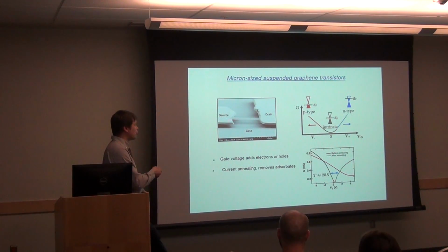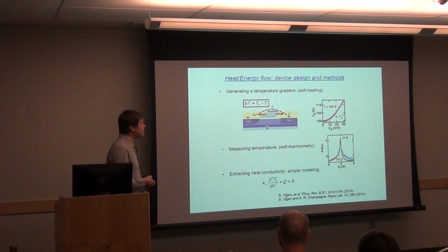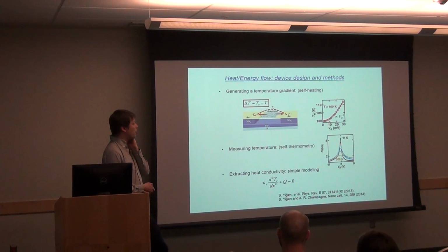And if we flow big currents through this, we bake it, and it basically gets cleaner, and you get the black curve, which is very close to the empirical one. So the idea why the experiment worked well and was simple was that the graphene was its own thermometer and its own heater. So to heat it up, we simply flowed current through it, and it got hot. And because we did the very detailed calibration, by applying a bias, we could measure the temperature going up. By measuring the resistance, you know the temperature of graphene.